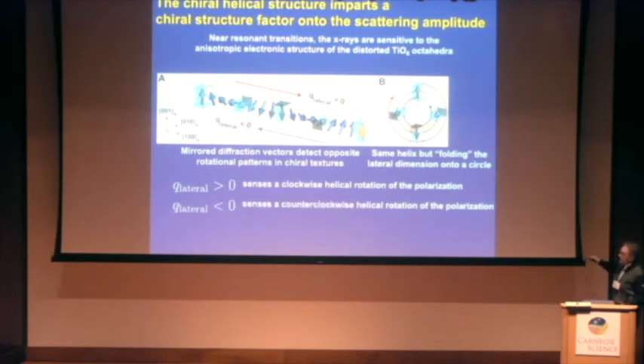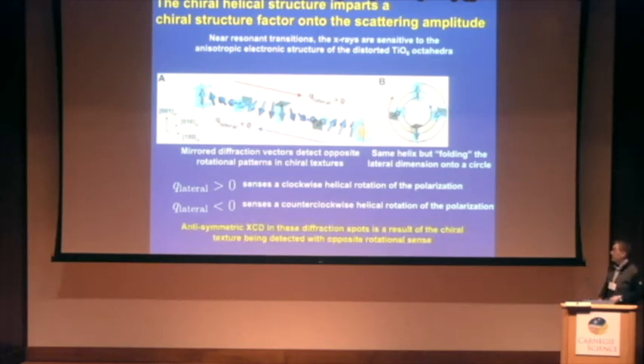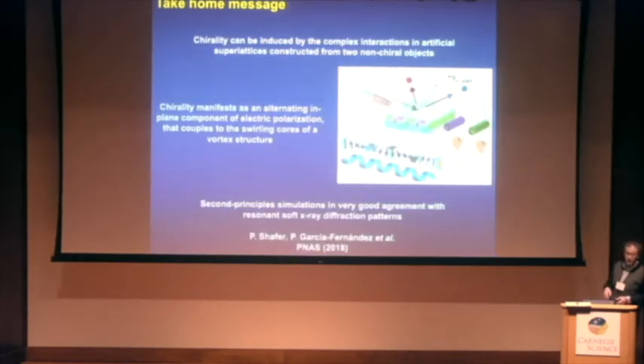The diffracted beams with a positive lateral component of Q sense a clockwise or counterclockwise helical rotation of the polarization, and therefore interact much better with the left-handed polarized light, while the negative Q lateral sense the opposite helical rotation of the polarization, so they interact much better with the right-handed polarization. So essentially, this is the take-home message.